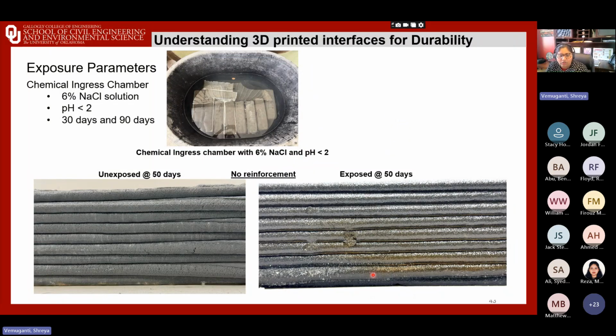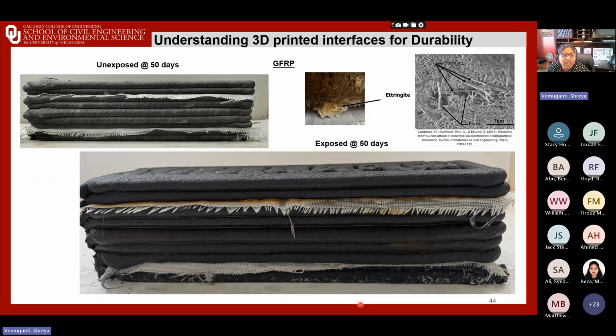You can see that dark contrast too. Now, if we look into these pictures, this is no reinforcement, right? We don't have any reinforcement at the interfaces, but there is, of course, some visible discoloration, and the surface also appears a little more pronounced. There is sort of more predominant discoloration at the interface than away from the interface, but it's again too soon to tell. 90 days might have more significant effects on the interface.